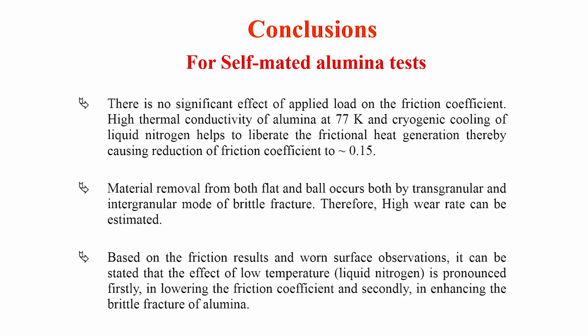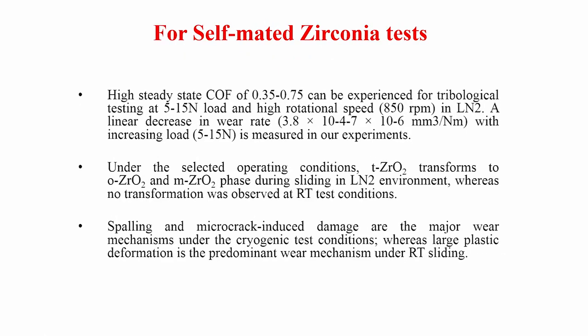In conclusion, for self-mated alumina there is no significant effect of load and material removal from both flat and ball by transgranular and intergranular modes of fracture. In the case of zirconia, a high steady-state COF of 0.35 to 0.75 has been observed at tribological testing from 5 to 15 Newton, with spalling and microcrack-induced damage as the major wear mechanisms under cryogenic sliding conditions. Thank you.